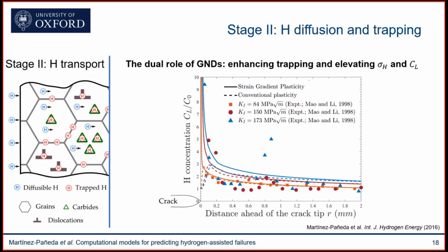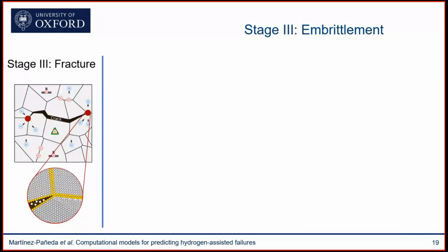We know that the cohesion arguments need higher hydrogen concentration than the higher crack tip stresses, and these GND effects, in my opinion, provide a solid argument behind them. So once you know how much hydrogen you have within your material, within your microstructure, then it's time to predict the fracture, the embrittlement process itself.